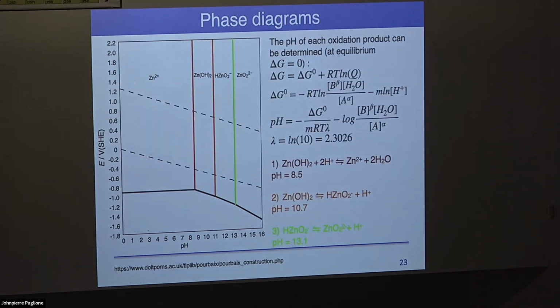In the regions you see here, you essentially have a pH acid-base problem. For example, in the equilibrium line here between Zn2+ and zinc hydroxide, you essentially just have an acid-base problem. Then you can go back to the Nernst equation and figure out where the equilibrium between those two species will be. If you do all the calculations based on the Gibbs free energy of, say, this reaction here, you can find that Zn2+ and zinc hydroxide will be in equilibrium at pH 8.5. You can actually construct these Pourbaix diagrams from first principles if you want to.